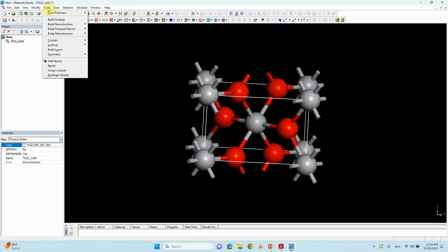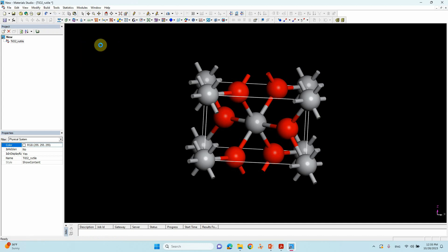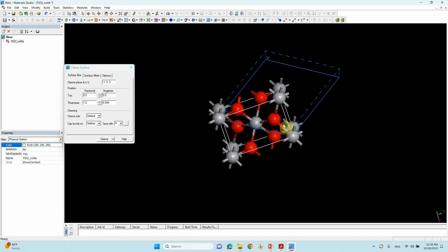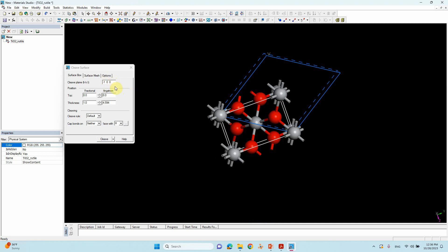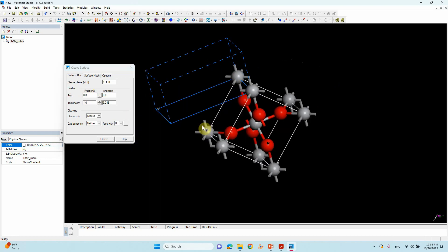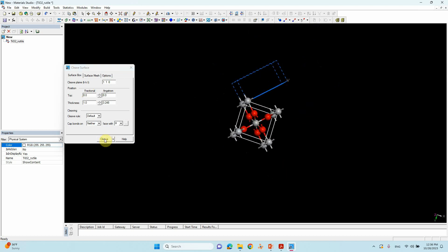To cleave the surface, go to Build > Crystal > Build Layers, then go to Cleave Surface. You will see Miller indices — the default is -100. Remove the minus sign and change 0 to 1 to get the 110 surface. Click Cleave to generate the cleaved bulk structure.